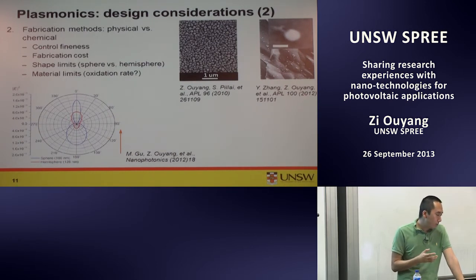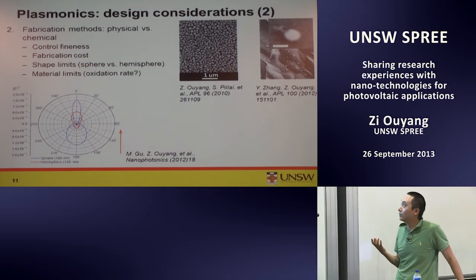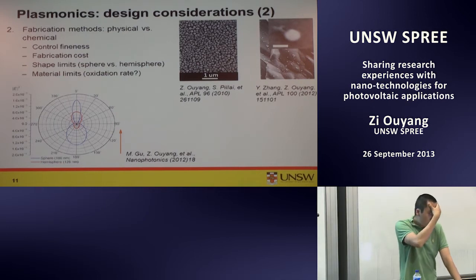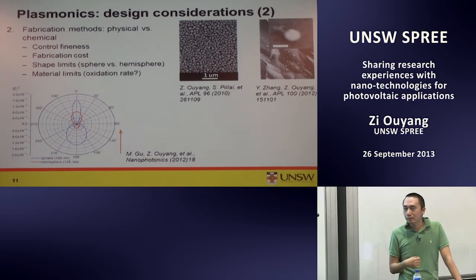So let's jump to another page. We know what material we use, and we see the fabrication method. Basically, there are two methods I just talked about: a physical way, deposition and annealing, and the other way is chemical synthesis. There are a few things you need to consider in choosing what method to use to fabricate these nanoparticles. First is the control fineness. I personally think the physical way is the simplest way. But the problem is you are very much limited by the control method. You can control the temperature and the thickness of the thin film you deposit, and you just anneal and see what's happening. So you don't have a lot of freedom to control the nanoparticles.